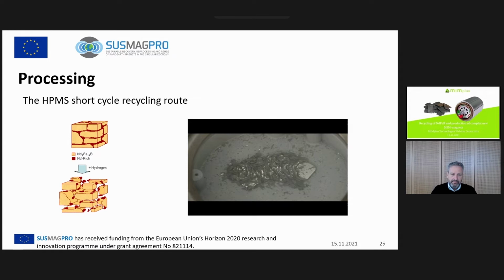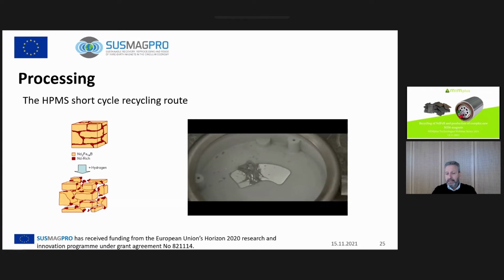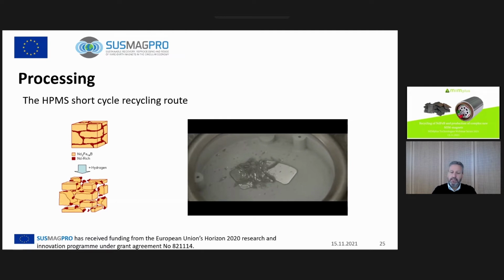And as in winter, when you have water that is freezing and expanding in volume, making a crack in the road, here this expanding of the volume leads to the magnet decomposing into a friable non-magnetic powder. And what you've seen here on the video, which I started again with a hard disk drive magnet, is that the corrosion protection coating that's on top is flaking off in large flakes and can ideally be sieved off.